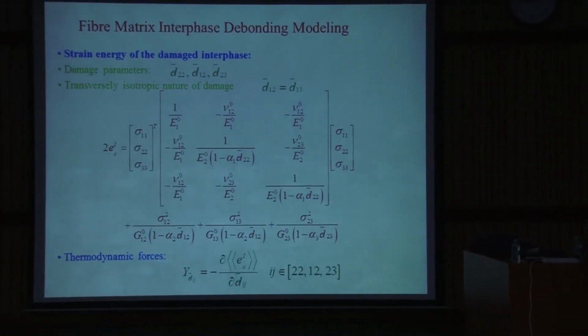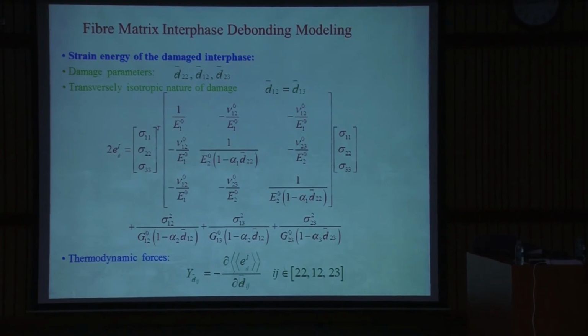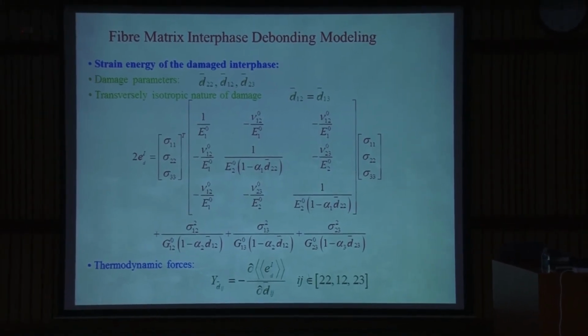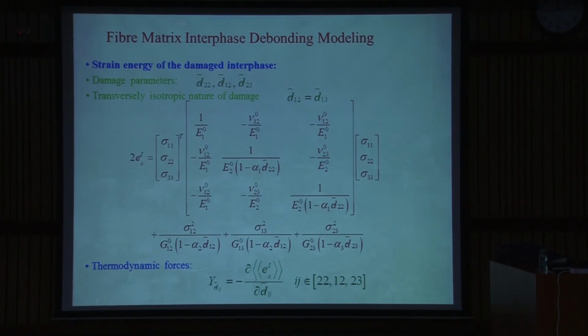So 2, 2 means in the normal direction to the fiber, then 1, 2 and 2, 3 are the shear effects. So your damage in the interface is going to affect your E2 modulus, and then also it is going to affect the shear moduli. Again, there is one more assumption, that this damage is considered to be transversely isotropic. So whatever you have in this direction is also in the same direction, meaning in the plane direction as well as in the thickness direction.